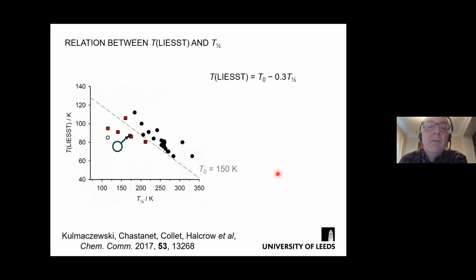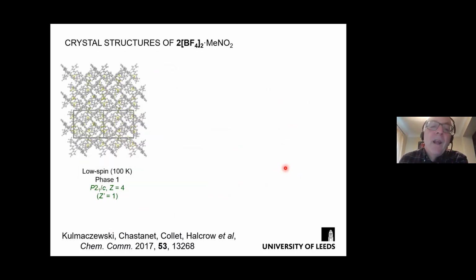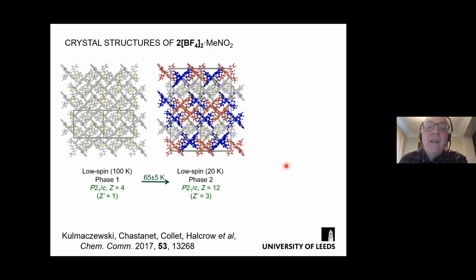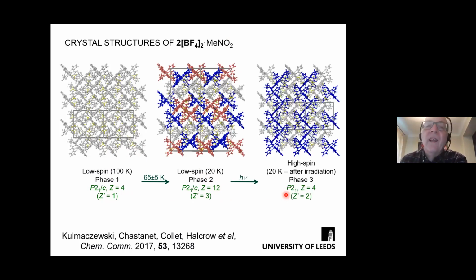And then he measured this one, and this guy is a lot more complicated, because when you cool it down, it does a phase change, a tripling of the unit cell. And it's still low spin here. These are all low spin molecules, but the unit cell changes, and then you irradiate, and it does another phase change. So there's a phase change occurring during LIESST relaxation, and then you warm it up, and by the time it's done the LIESST relaxation, it's reverted back to this phase.